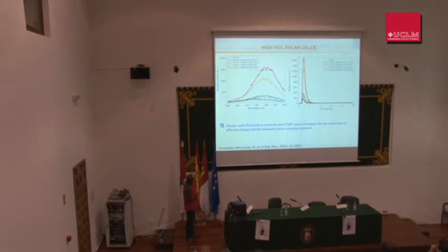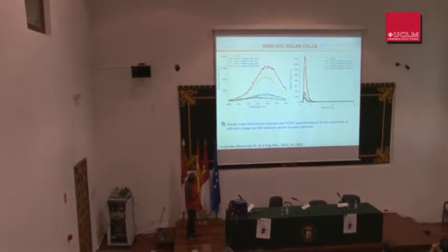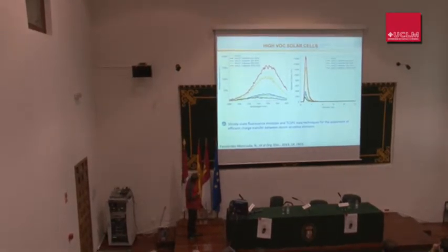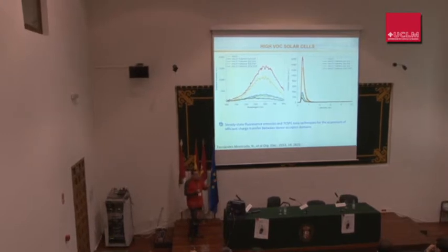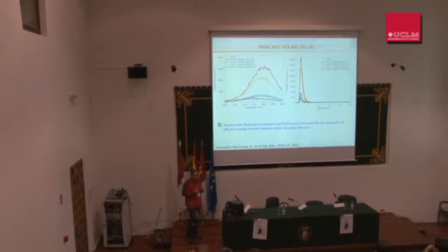Fluorescence, as I say, is very important. You can see here, this is the molecule by itself. This is the emission. And then when you mix with fullerene, the emission goes down. And the reason is because you quench the excited state of these molecules, and that's good because it tells you that you form excitons. But the question is, these excitons now can do two things.